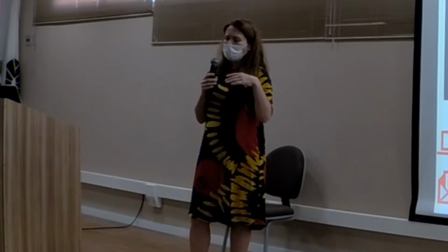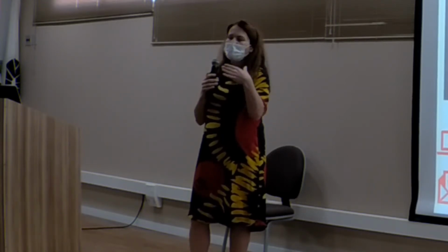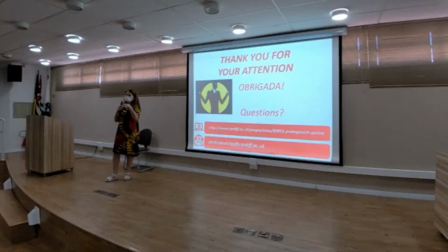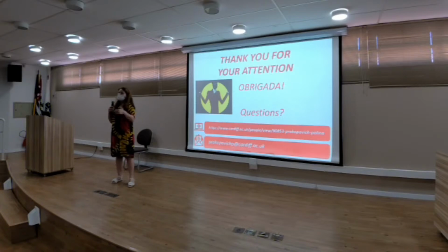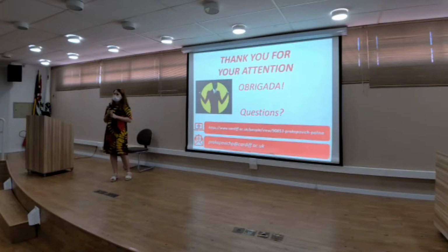If you have strong electrostatic interactions within the layer-by-layer construct, your release will be longer, and it's a more stable construct as well. When you have very weak electrostatic interactions within the layer, your release will be quite fast because the construct tends to break down much more rapidly, as there are no strong forces within it. So zeta potential has a great effect on the stability of the construct, on the release profile, and on the structure of the polymers as well.